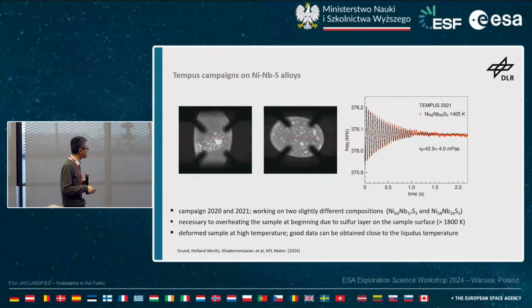That's why the temperature range is rather limited. For those of you who are not very familiar with this kind of measurement, basically we are doing an oscillating excitation of the sample. And what you are looking at here is the damping of the sample once you switch off the oscillation. If this experiment is clean, you see this kind of curve.